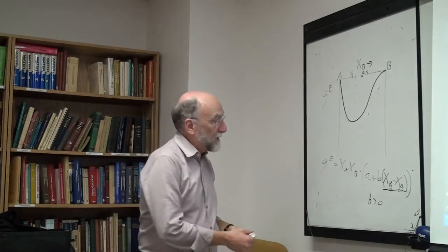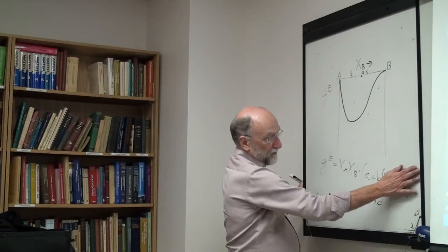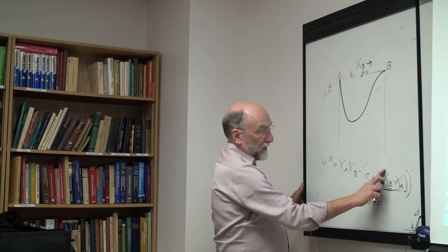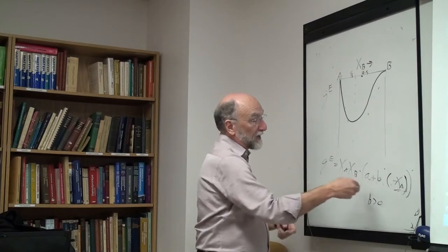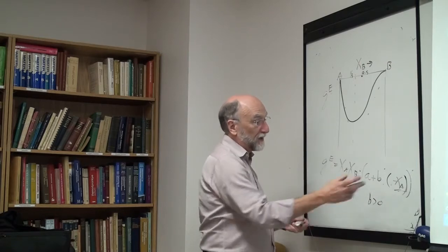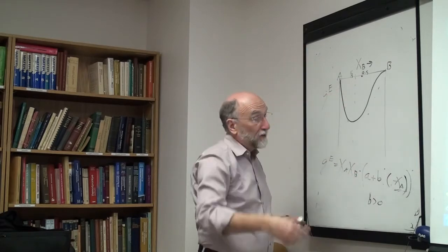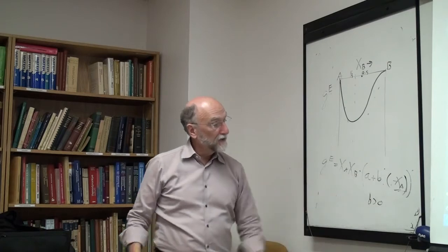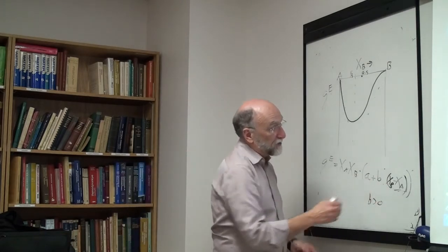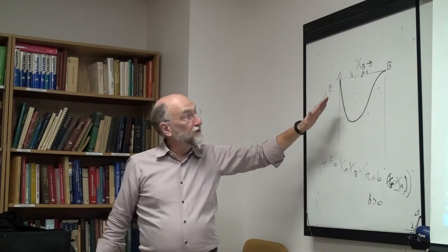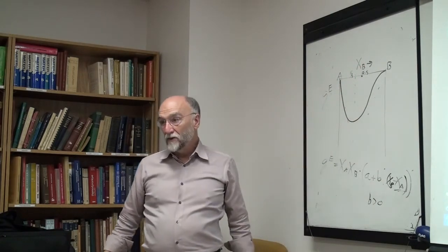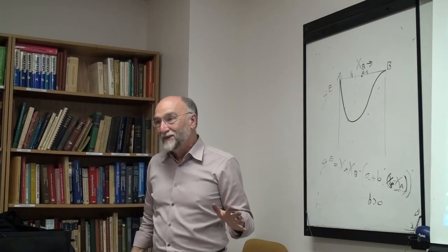And it doesn't matter, you could say, let's make it A plus, let's take that term out and just use a straight, but it's the same thing, that could be rearranged. That term still gives you the same affair, because it can be rearranged to a Redlich-Kister, so you don't get around it that way. You use a subregular solution, you shift the peak, but you change the shape of your curve, and often this is not what you really want to do. Sometimes it is what you really want to do.